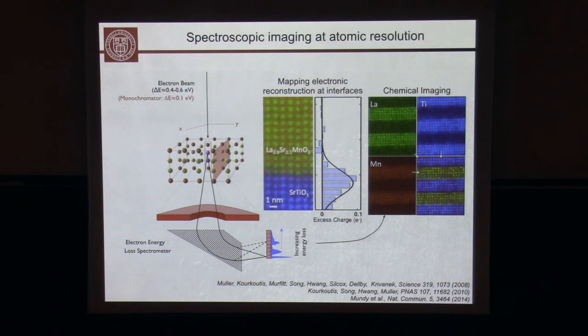Yeah, so if you want to get really good spectroscopy, you need to be within 50 nanometers or so. There's plenty of work that goes to 30 nanometers. We can certainly look and get beautiful atomic resolution images at that. But in spectroscopy, you're much more sensitive to beam tails. And as you go to thicker samples, you get beam broadening.